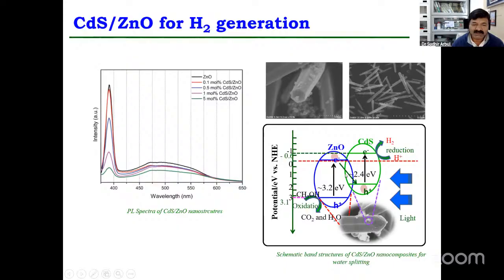The conduction band electron from zinc oxide reacts with holes in the cadmium sulfide. At the same time, the electron present in the conduction band of cadmium sulfide is available for photocatalytic reactions. Here what we did, 50% electron-hole pairs we sacrifice, and at the same time, 50% we use for our reaction. So this is the beauty of this coupled catalytic system.